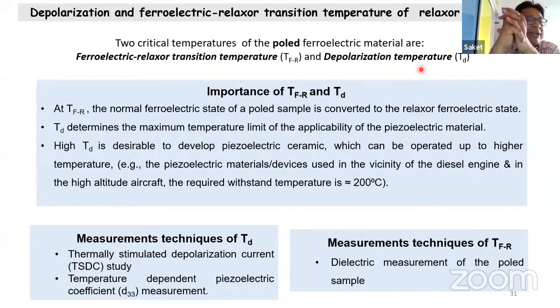Okay, and another important temperature is the ferroelectric to relaxor transition temperature, because we get better energy storage performance in the relaxor regime. So these two temperatures are very important for any application. And here you see the measurement of these temperatures by very sophisticated techniques.